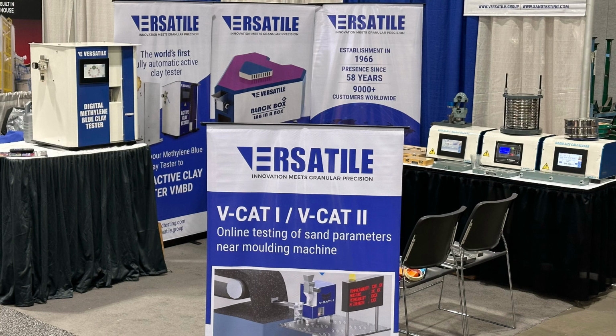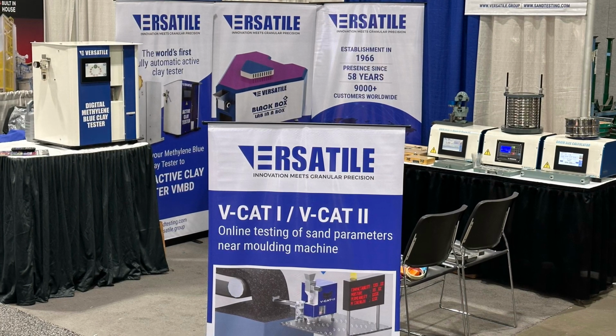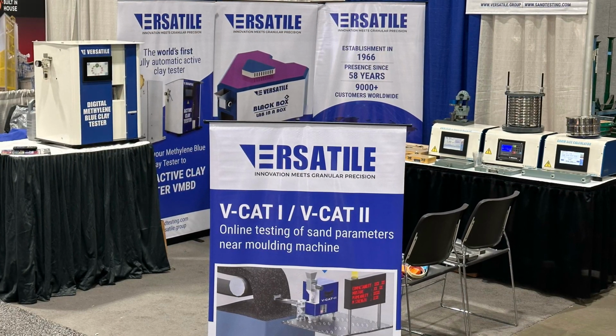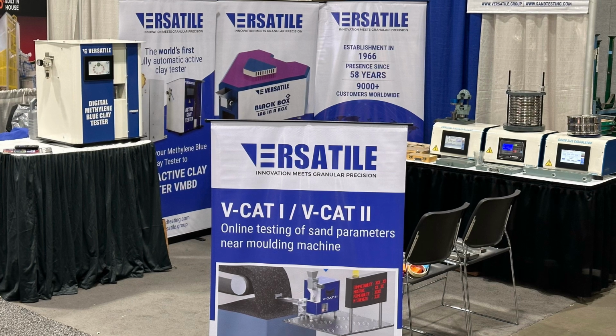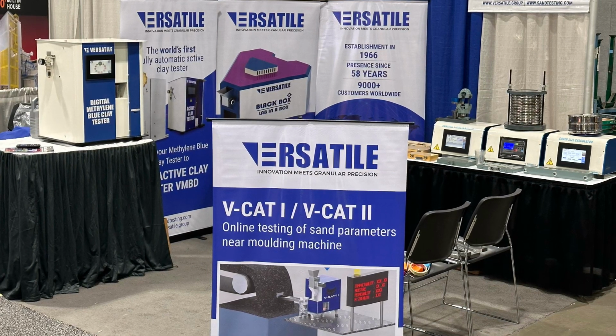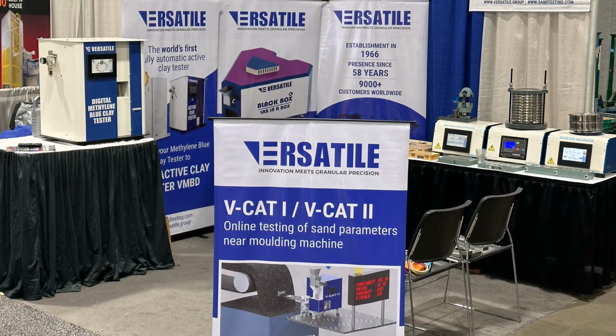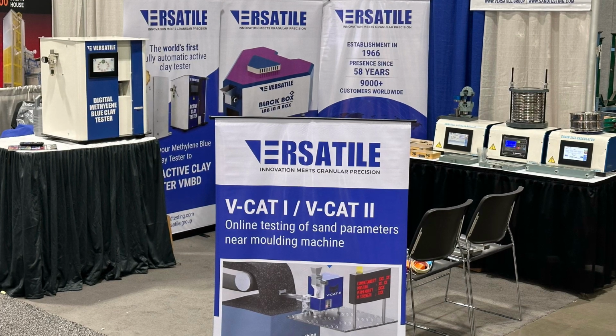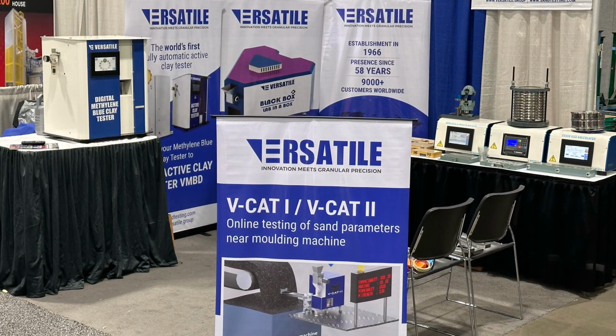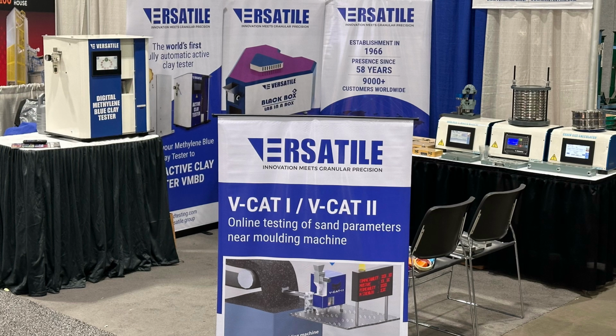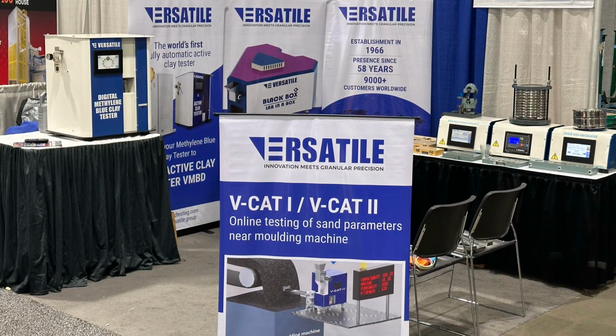And for the strength tests? You need specific machines: shear strength testers, tensile testers, splitting strength apparatus, and crucially, to make the little sand pucks for testing, you need a standard sand rammer and specimen tubes. Can't do much without properly prepared samples. Right. Consistency starts at the sample prep. Definitely. Then you need a permeability meter for checking gas flow.